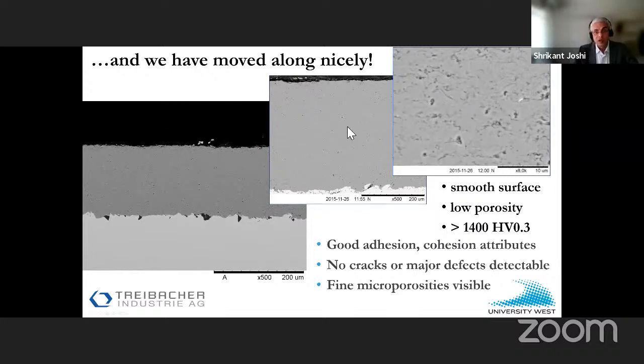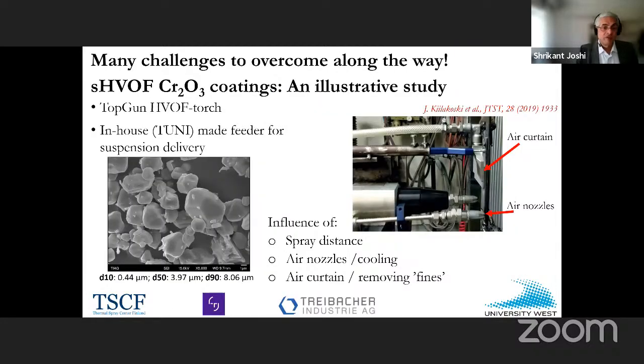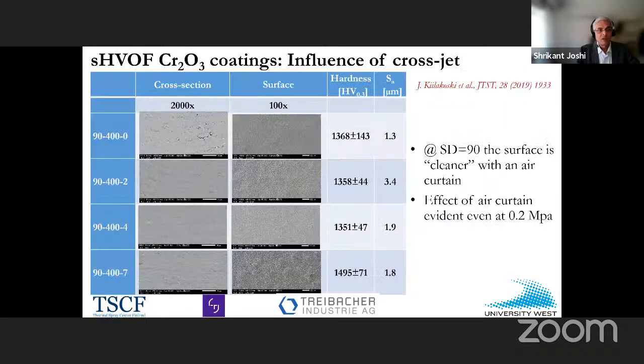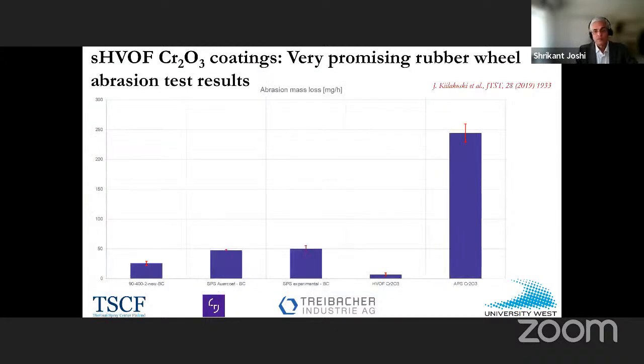We get very good chrome oxide coatings, this was all with 40% solid loading, and we've built on that further. First was to see if we could carry that to an HVOF, and this is part of Yarko's PhD work during my short stint at Tampere. And if you manage to optimize the process right, and we tried several things here, looked at spray distance, looked at employing an air curtain to reduce fines, you can get really good coatings, even using suspension HVOF, right? Which gives darn good wear properties, right?